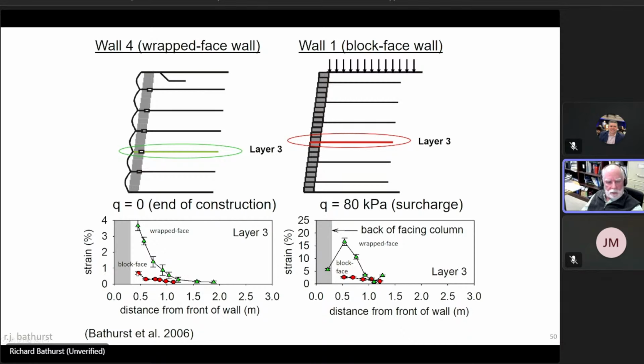If we look at this curve at the bottom left plot, you can see the strains in the reinforcement are quite low compared to the strains at the same nominal locations for the wrap face. This is because the hard facing helps to carry the loads that are being generated by the fill, whereas the wrap face is too flexible for that. This difference in performance persists when we surcharge the walls, and that's shown on this plot to the right.